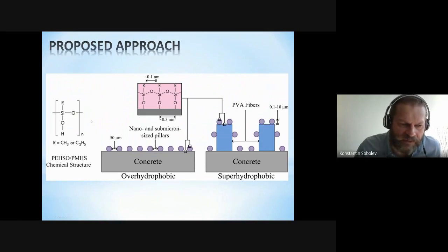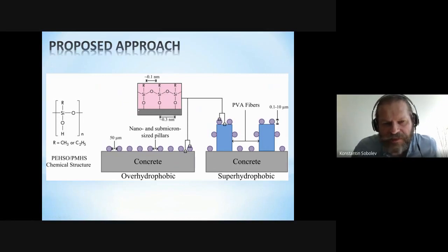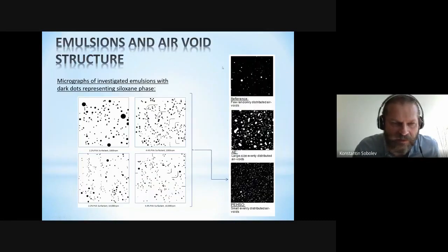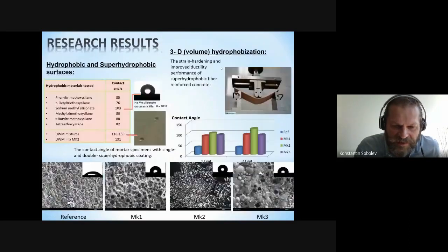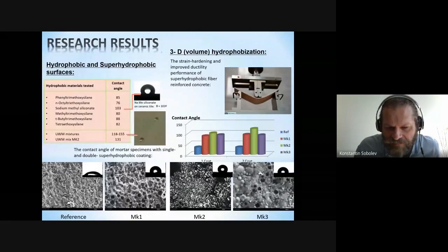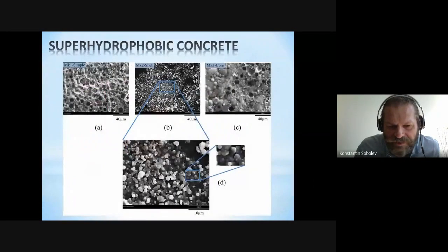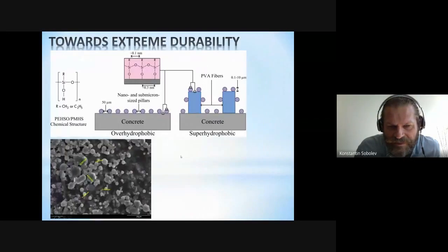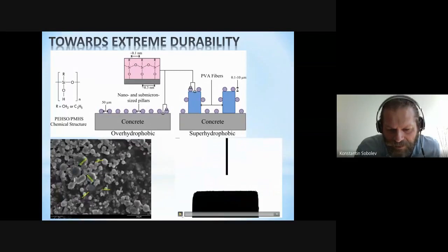Basically, we incorporate polyethylhydrogensiloxane agents, which can provide a chemical bond with any silicon structure or silica aluminate structures. We also incorporate nanoparticles or nanostructures into the surface. You can see that these can be designed with particle deposition, so we can control the roughness, and with roughness we can control the surface. You can see how the structure is designed with particles.